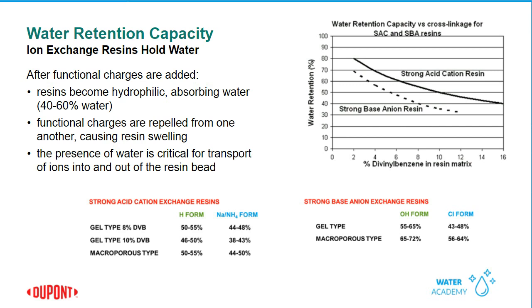The water retention capacity for strong acid cation resins is a measure of those cross-links. And so when resins are exposed to different oxidants, we see an increase in the water retention capacity because those polymer chains are breaking due to oxidation. And so the water retention capacity is an important parameter that we measure in the production of our resins, as well as when we're evaluating used resins.